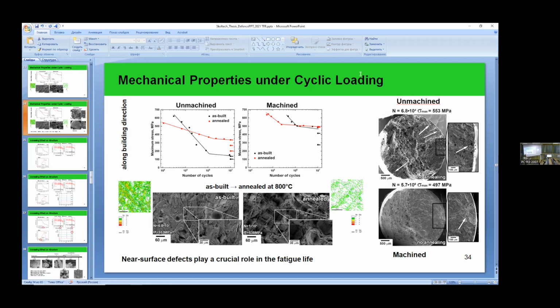Yes, unmachined. In the case of cyclic loading, there are two stages of sample fracture. The first is the formation of the crack, and the second stage is propagation. In the unmachined samples, we already have the formed defect which initiates the crack. So the first stage is really short for these samples, and the main contributor to the fatigue life is the crack propagation time. In this case, for the annealed samples, since we have more ductile behavior, the fatigue life is higher and it's visible.